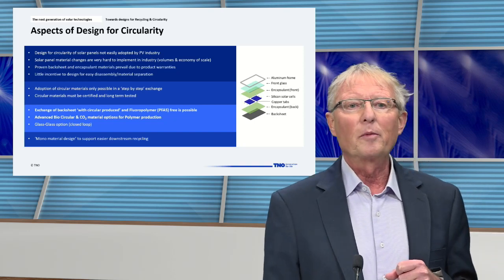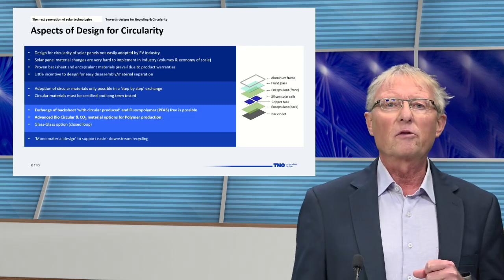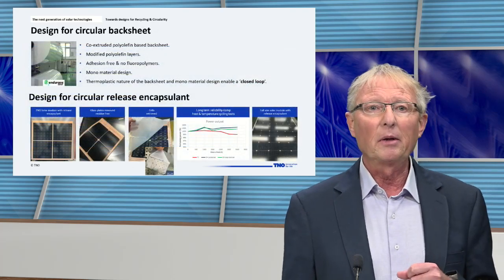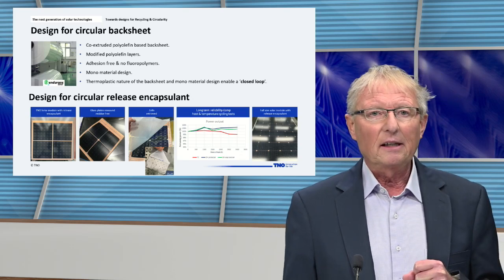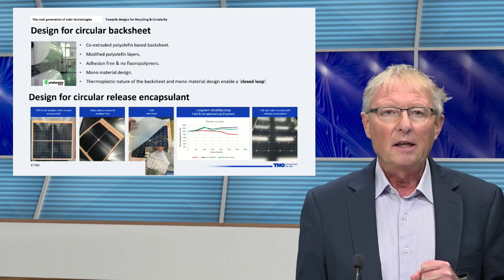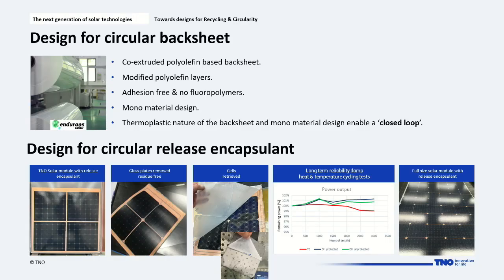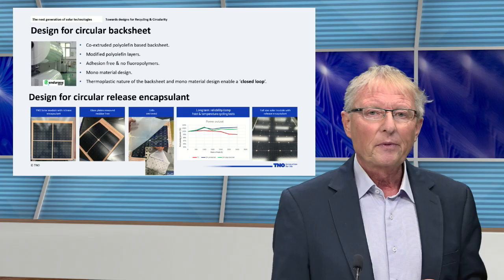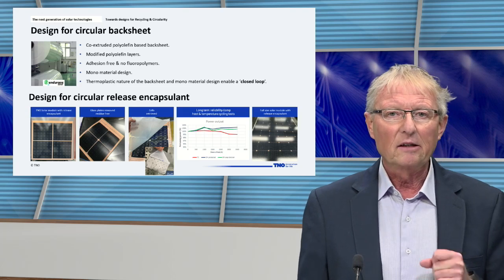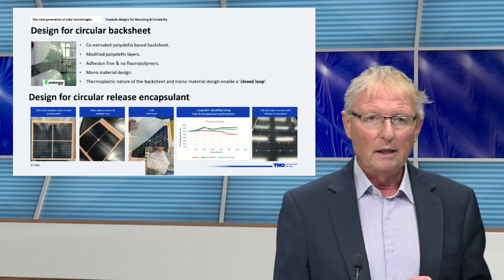Very important is the monomaterial design to support easier downstream recycling. Here I have an example of such a monomaterial design. It's in the form of a circular backsheet. It's a co-extruded polyolefin-based backsheet, which means that all the layers are made from one material, and that is polyolefin. So they are modified to fulfill all the requirements of standard backsheets, and there is no adhesive in between the layers. So this monomaterial is of thermoplastic nature, and that helps us a lot to recycle, reuse, and it is therefore also a closed loop material.